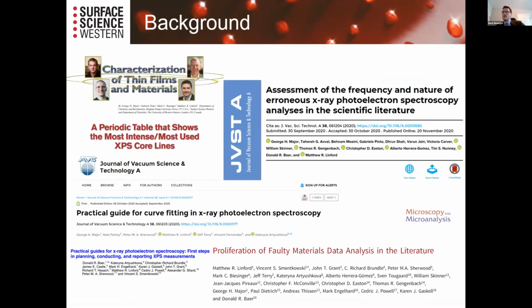Others have noted that there's been a lot of issues in the literature with interpretation of XPS spectra, and in particular, the interpretation of the transition metals XPS. There's been kind of a proliferation of faulty data ongoing within the community, where there's some citing of erroneous data, and this is even happening in high impact and well-regarded journals. So the point kind of is that XPS is not just a point and shoot type technique. There is a need for expertise on both the analysis side and on the interpretation side of things.